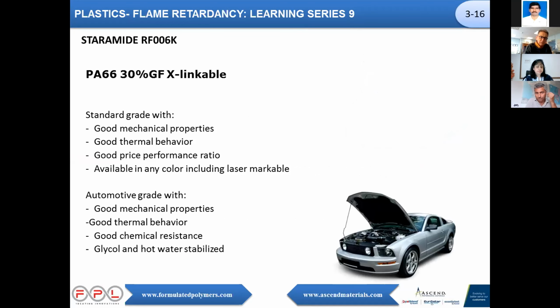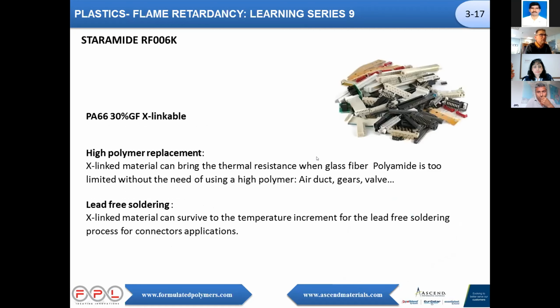Then if the material needs to be more stiff, needs to withstand more heat, more HDT, we have this polyamide 66 with 30% glass, which is cross-linkable, which finds use in automotive applications. But not only in the automotive. You know, there are some connectors that are not flame retardant, they're only there to pass a kind of signal, but can fail under high heat. And then you can use this product too, of course.